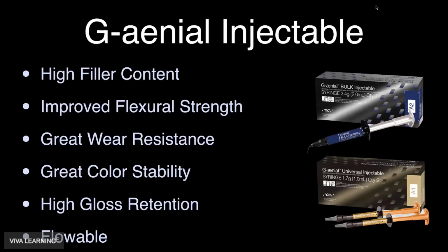So how did GC do this? How did they figure out how to sort of conquer the viscosity barrier and create a material that has an injectable viscosity and yet has a high enough filler percentage that it has all of the same physical properties as all of the other sort of nano fill composites that are out there on the market today? Well, they did it basically in two ways. One was an adaptation of what we already knew. The smaller the filler particles, the more of them you can put in without adversely changing the